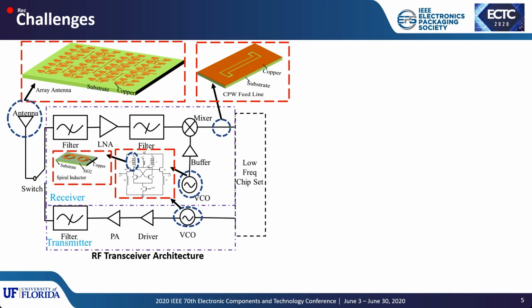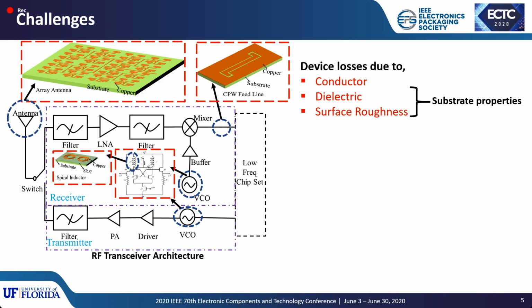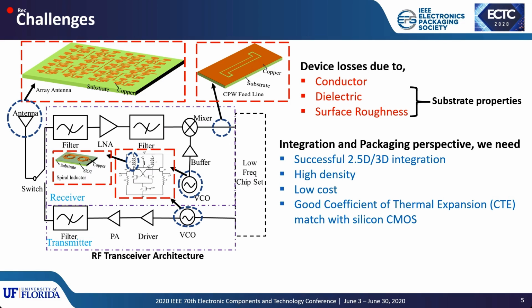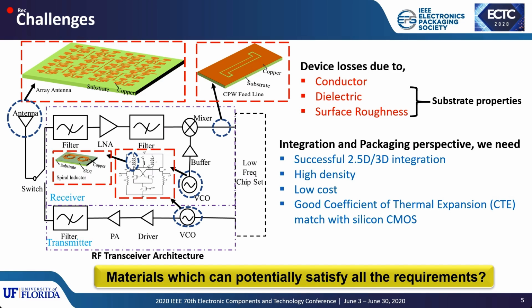So because of these devices, you're going to mainly have three types of losses at high frequencies. One is the conductor loss, the dielectric loss, and the surface roughness loss. All these losses increase as a function of frequency. The dielectric and the surface roughness loss are completely substrate properties. Also, from the perspective of packaging and integration, we need successful 2.5D or 3D integration with high density, low cost, and a good coefficient of thermal expansion match with CMOS silicon. So basically, we are looking for materials which can potentially satisfy all these requirements.